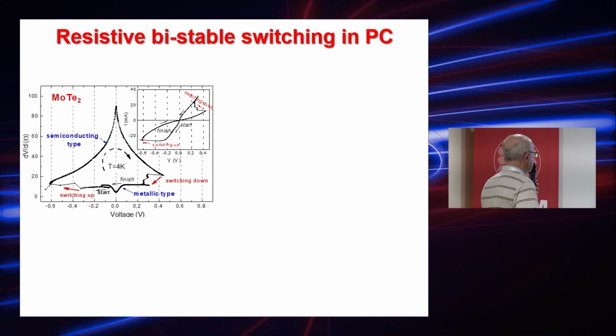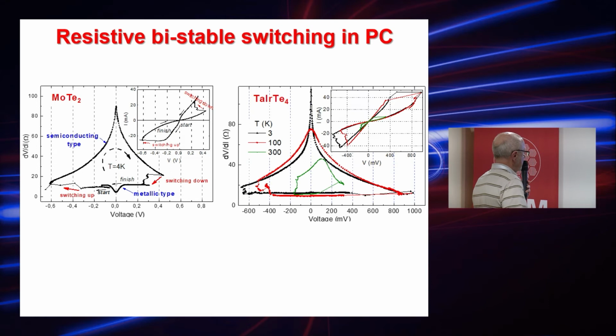data of switching. When we start with the low resistance state, then at some voltage we observed change of resistance to the high resistive state with semiconducting-like behavior, and then at opposite voltage we observed switching back to the metallic, low resistance state. So you see that by applying a voltage, we can change point contact resistance depending on the voltage. Such dependence exists also with increasing temperature.